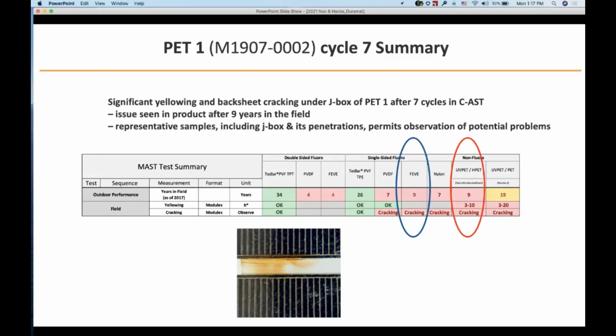And it also highlights the necessity of using representative samples, including a J box, its penetrations. Penetrations that we introduce into the backsheet allow for different moisture ingress. And of course, the heating associated with the junction box under light is representative. So using representative samples, a feature of combined accelerated stress testing where we use four cell mini modules, permits observation of potential problems.